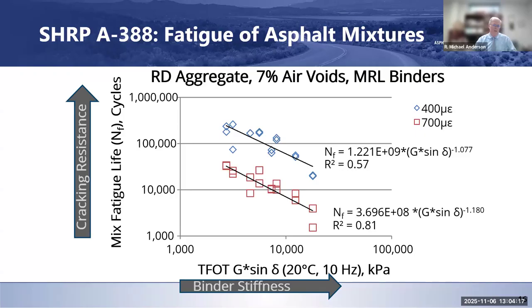What was unique about it was we had a couple binders that looked to have very similar properties, except they differed in one area. And you could see a difference in what the CT index values were. It wasn't like a wild difference or anything along those lines. And you could argue that it would even be within testing variability, but it was enough to indicate that, okay, perhaps it does pick up on part of that. We know that CT index picks up on stiffness. That's part of it, but how does it do in regards to picking up on something like relaxation? And so that's a question that comes up. How does it characterize the materials?